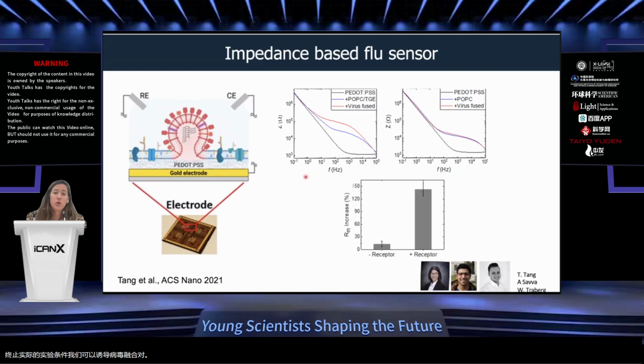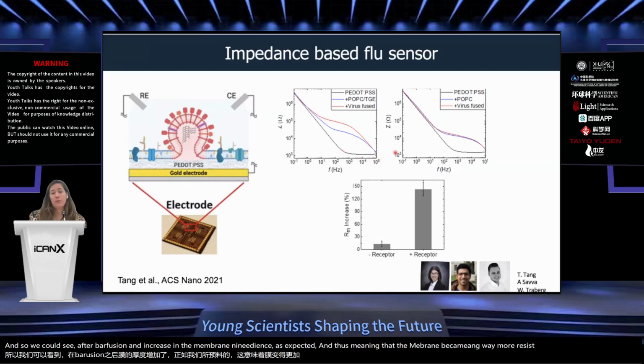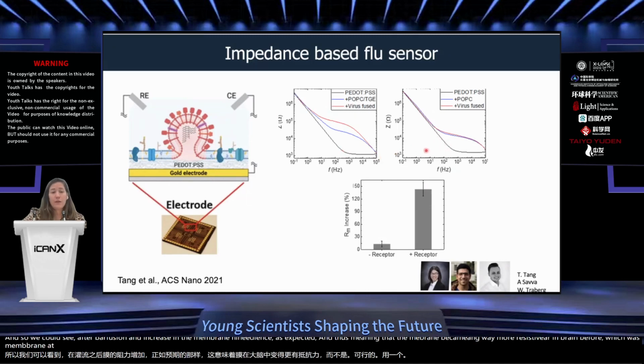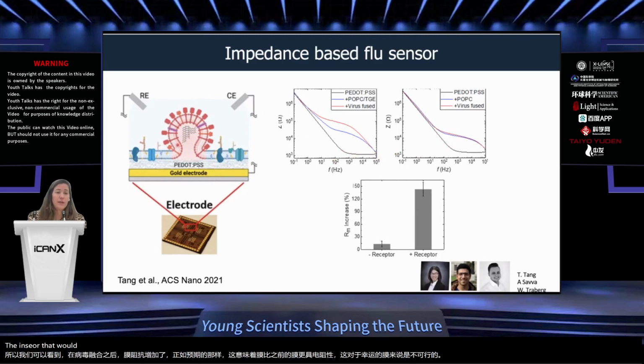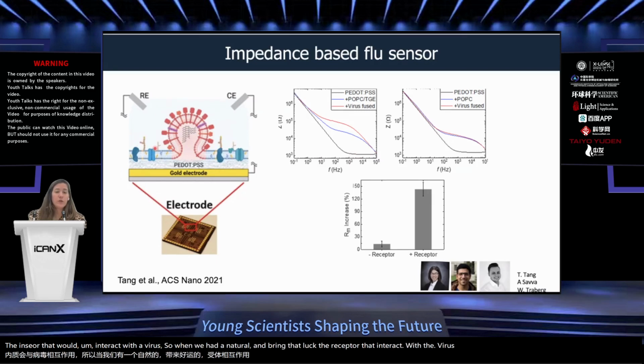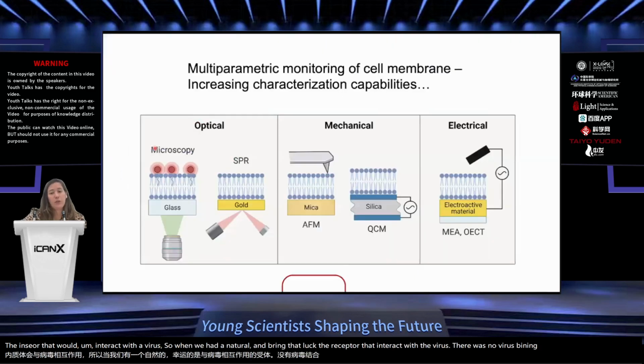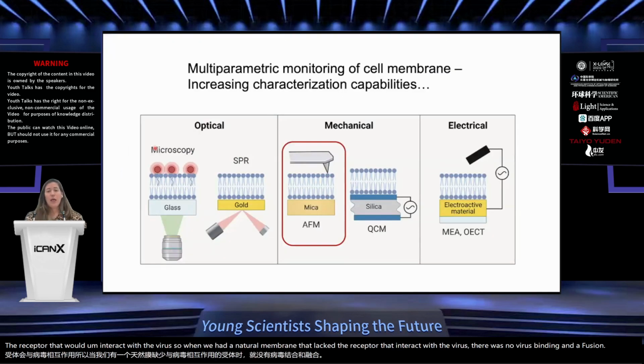And so we could see after viral fusion an increase in the membrane impedance as expected, meaning that the membrane became way more resistive compared to the membrane before, which was not visible with the membranes that lacked the receptor that would interact with the virus. So when we had a natural membrane that lacked the receptor that interacts with the virus, there was no virus binding and fusion.